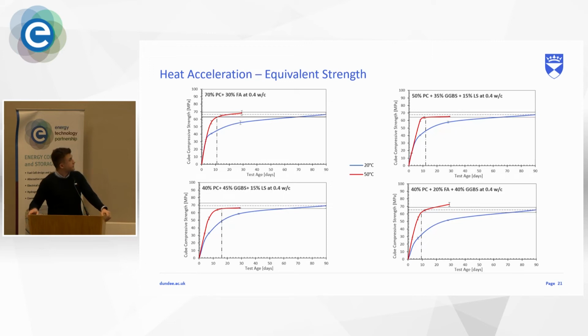So the graphs are showing compressive strength gain against curing time. The blue curves represent the standard curing process of low carbon concrete. The red curves represent the accelerated curing process at 50 degrees for the very same components, the identical samples, just cured at different temperatures: one is cured at 20 degrees and the other at 50 degrees.